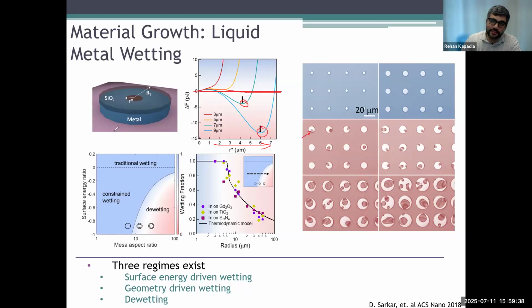But essentially, what we also think is happening, and this is true for any material, any time there's a nucleation and growth event, is that you also have what would be called subcritical voids, where you're creating nuclei and they're disappearing. We think that's what's happening in these materials because they don't de-wet, but you're probably still creating and eliminating voids over time. In liquid phase, that's fine because those voids are being created and eliminated. But once that indium turns into solid indium phosphide, those voids, however they were at the time, just stay frozen there. And that's exactly what we think we're seeing.